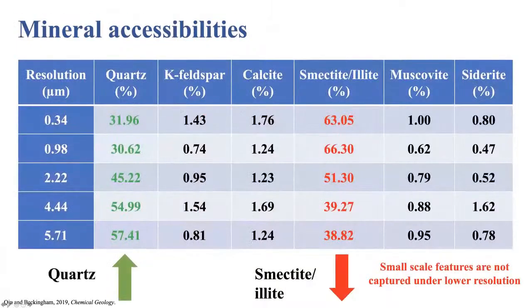So here's the accessibilities with different image resolutions, where we see an increase in quartz accessibility with decreasing resolution, and a decrease in smectite illite, or our clay mineral here, with decreasing resolution. So as you decrease the image resolution, it's no surprise that you have a hard time capturing the small scale features.